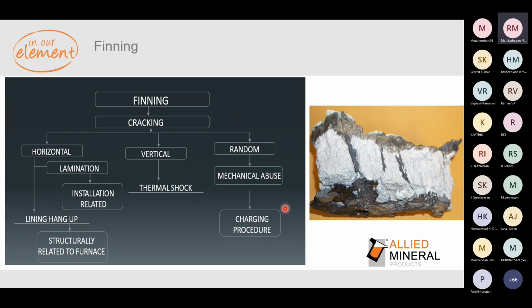When it comes to lining hang up, it's mainly because, as I said in the initial stage when we were discussing grout, the grout has to be as smooth as possible. So we have to minimize the number of repairs we are doing to the grout, because as you increase the amount of repairs, the grout is not going to be smooth. When the lining is under hot condition, when you heat up the lining, it expands, and when you cool it down, it does not contract in the same fashion. Wherever there's a projection in the grout, these projections will not allow the lining to settle down smoothly, and it creates horizontal cracks, which are very hard to seal up, and there is a high possibility of metal penetrating those cracks. So we normally call it structural related. We need to take care of it.